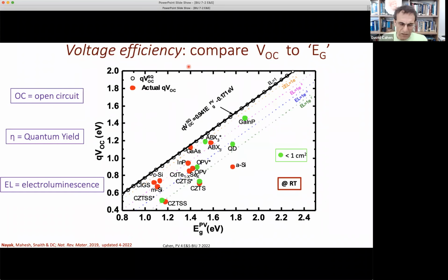Now we can compare the voltage that I can get out to the band gap of various solar cells. And I would like to get all of the band gap out, but that is not possible. I've already shown you the various causes for limitations. And I can calculate this formula to take into account the Carnot efficiency and the étendue losses to say this is where my efficiency is if I had a completely ideal cell. And here's gallium arsenide, in terms of its voltage efficiency very close to that. And the nice thing about the halide perovskite is that they're also getting close to it, at least in small cells. And the rest is quite far away, and generally the only exception is gallium indium phosphide.